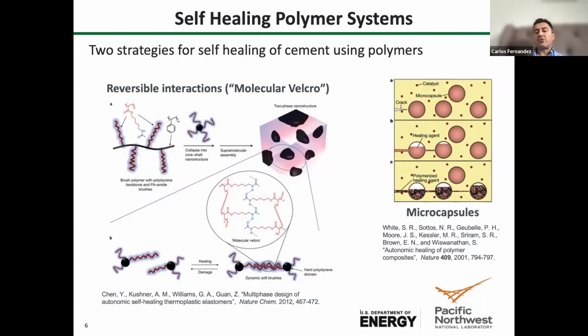It's not true self-healing, but it's actually a filling event where, as long as you have enough of the catalyst, cross-linker, and monomers, you're going to have fractures being healed by filling the fracture due to the polymerization and cross-linking of the polymer. In our case, we don't need capsules, we don't need a catalyst. All we need is to have the polymer already polymerized and distributed homogeneously in the cement matrix. And then because it's hot, that polymer, particularly the smaller strands, will have mobility to be able to dynamically and reversibly exchange bonds with the cement, and in the presence of fracture, be able to heal that fracture.